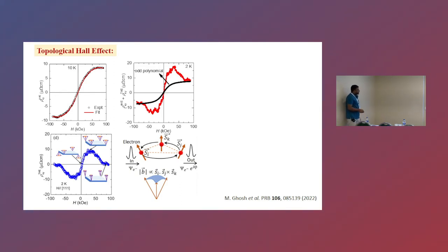So at zero field, we have both kinds of domain, and their corresponding spin chirality will be equal and opposite, so it will cancel out. That is mentioned here, like with the simple model. But as we increase the field, there will be asymmetric canting. That's why you have non-zero spin chirality in a particular direction, and it will increase and get saturated. And what will happen when you apply a large field? Their angle will try to close, so the solid angle will drop. That's why you are getting a decrease.